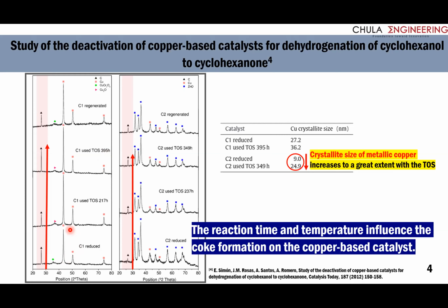Coke on C1 was deposited at 395 hours, while about 5.64% weight coke on the C2 catalyst was observed at 349 hours. The ratio between the intensity of the peak associated with crystalline copper and the intensity of the characteristic peaks of carbonaceous species also decreased during the reaction, probably as a result of the coke deposition. You can see the crystalline size of metallic copper increased to a great extent with the time on stream.